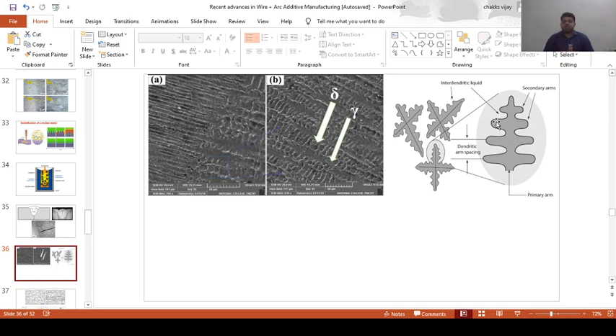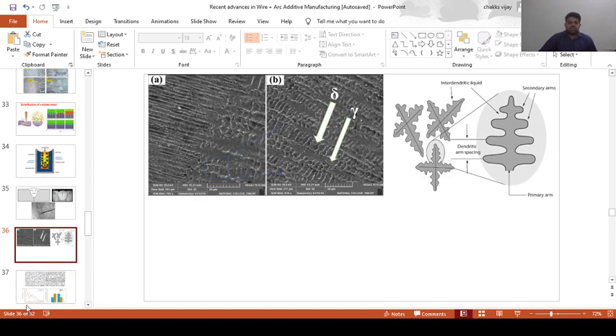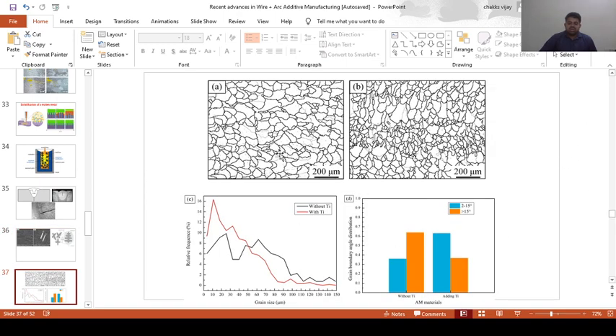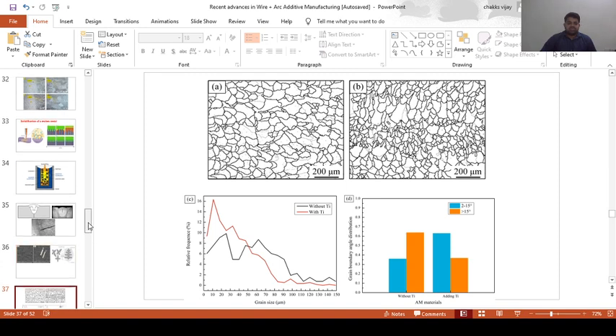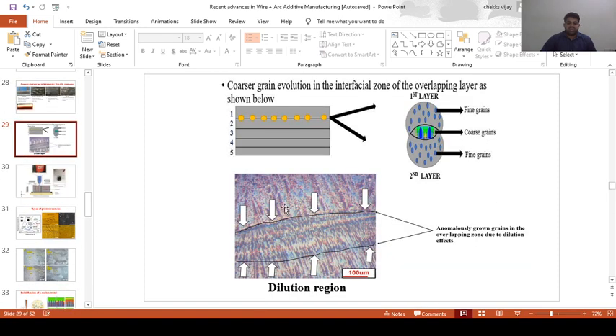So based on the secondary dendrite arm spacing, we generally say how far the solidification rates go. Just for knowledge, I included this slide, and here we can observe how far grain refinement could be possible, especially at the interface. Here you can observe very coarse grains in the interfacial region. So in the interfacial region, coarser grains are developed.